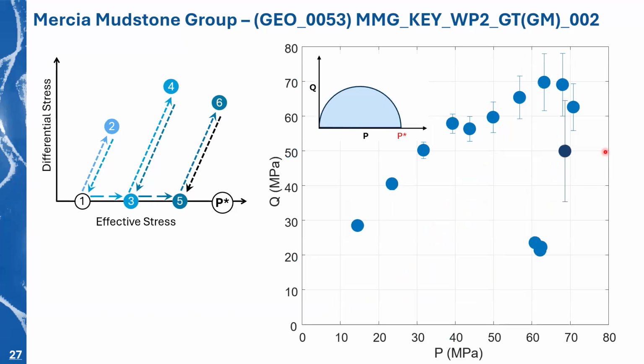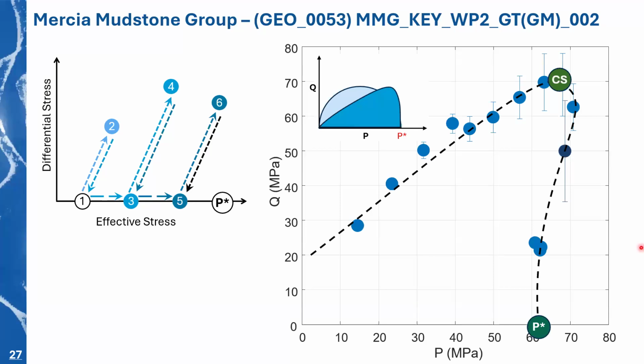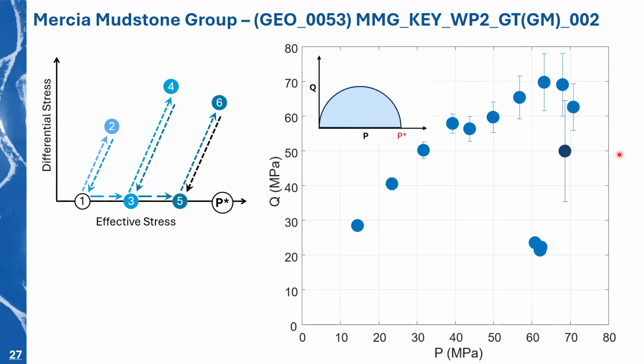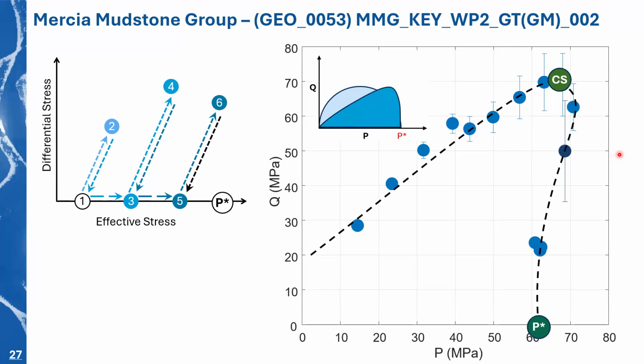For the yield curve for this one, we've got quite a similar shape to the Ancholme Group curve that we saw before. So rather than the nice semicircle, we again have a very elliptical, asymmetric yield curve. I've highlighted one of the points in a darker blue color. This one was done at a much, much slower strain rate than the others, but it fits in with the same trend. If you look at the scale on this one, it's quite different to the Ancholme Group one I showed you before. So we're going up to 80 on the Q on the differential stress, whereas we were maybe at 5 MPa on the Ancholme Group one.